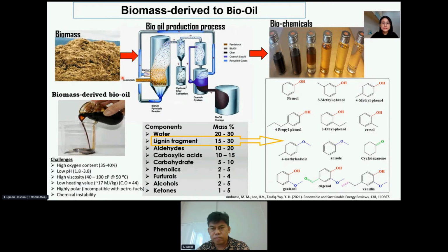However, the bio-oil cannot be used directly for further applications due to some limitations, such as its high oxygen content, which is unstable during storage, and it has high acidity, high viscosity, and very low heating values that cannot be used for fuels or heating processes, and it shows a high polar component, which is incompatible with organics or petrol-based fuel mixing. And then it is also chemically unstable, right?